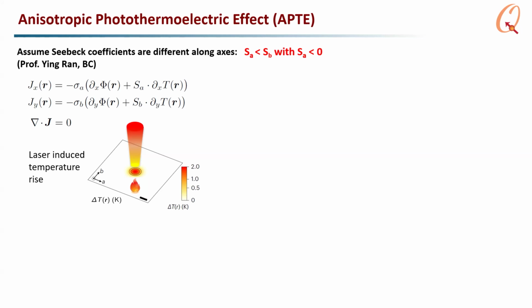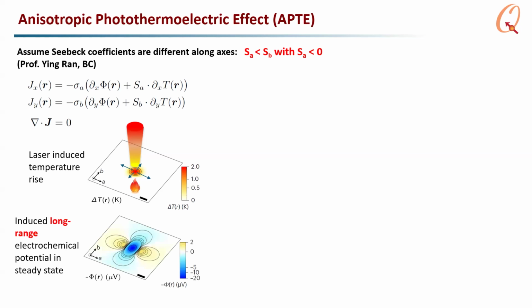But here we have anisotropy, where the Seebeck coefficient along the A-axis is more negative than along the B-axis. What that means is that more electrons are going to come out along the A-axis than along the B-axis. This induces a pileup of electrons, more along the A-axis than the B-axis, which induces a long-range electrochemical potential that tends to circulate the electrons from the A-axis to the B-axis. If you had isotropic thermoelectric coefficients, the long-range electrochemical potential could exactly cancel the Seebeck potential, and you would get no photocurrents. But if it's anisotropic, this leads to circulation of currents rather than the current stopping.